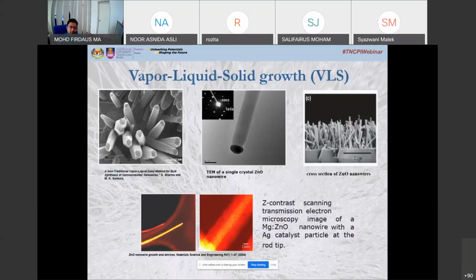So the same approach is used to develop zinc oxide nanowires, where here silver was used as a catalyst. You can see it from the figure. This is the tip of a single crystal zinc oxide nanowire. So this tip is the silver, and this is the cross section of the zinc oxide nanowires. So this confirms we can synthesize zinc oxide nanowires using the same method.